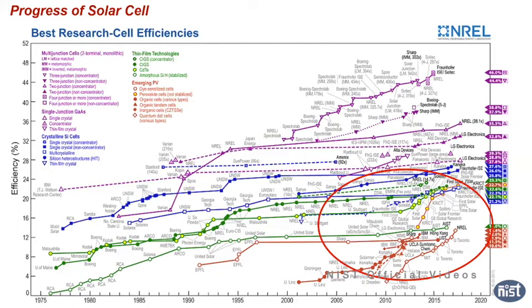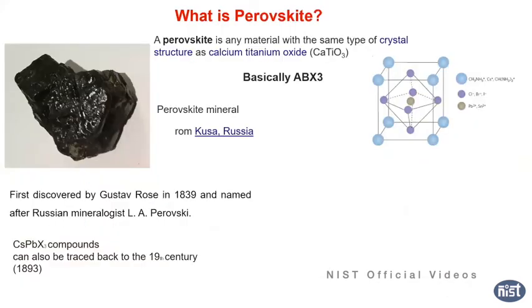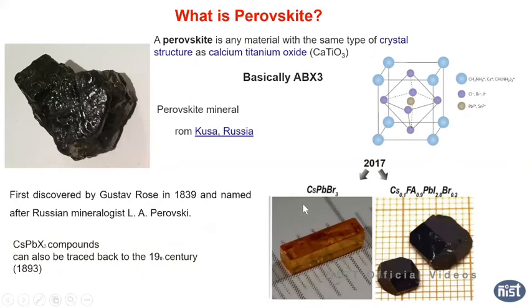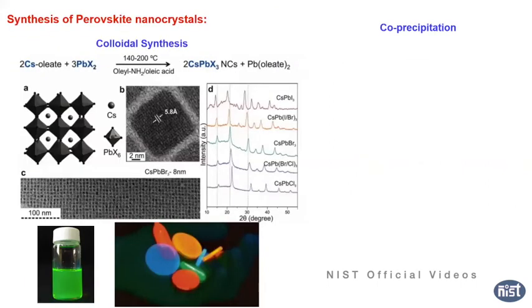But it's still lower than the perovskite. So we need to focus on other technology to improve the solar cell. So I go first to the perovskite part. It's another kind of semiconductor. Everybody knows that, physics people. It's a calcium titanate structure, ABX3, a perovskite structure. But we are most interested in not oxide perovskite. It's a halide perovskite, like cesium lead bromide, cesium formamidinium, or methylammonium lead iodide, this kind of organic-inorganic. Like here you can see it's a colloidal synthesis. Again, colloidal nanocrystals.